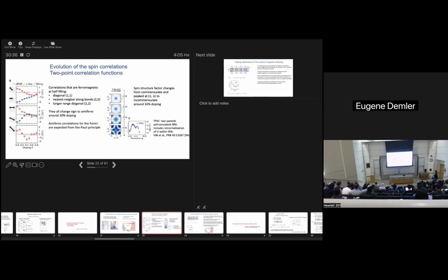Again, there have been many experimental measurements done in this case by the group of Immanuel Bloch. Let me focus on just a few. What they measure is the spin correlation function. In this case, they're looking at diagonal correlations as a function of doping. And what you see is that close to one fermion per site, that was our antiferromagnetic Mott insulator, on the diagonal we expect to see ferromagnetic correlation. Indeed, this correlation starts being ferromagnetic. But then with larger doping, they change and they become antiferromagnetic at longer distances.